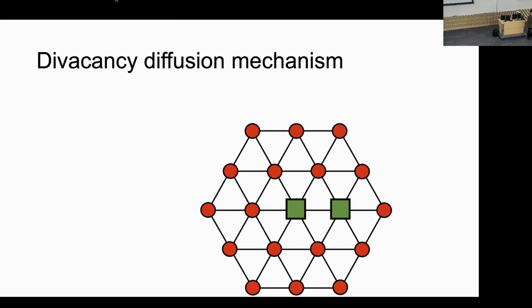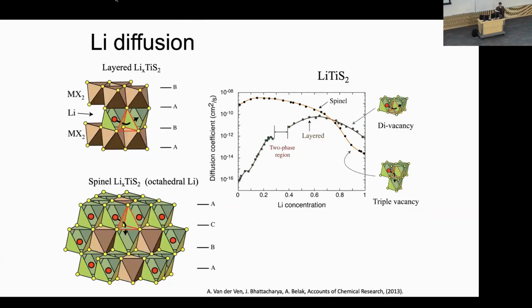It's huge, and that's why in this picture right here, the diffusion coefficient drops by orders of magnitude. What's happening here? Remember that plot I showed you with the C lattice parameter? This is for a layered material. So remember, the C lattice parameter is more or less constant up to here, and then it starts to drop just like this diffusion coefficient.